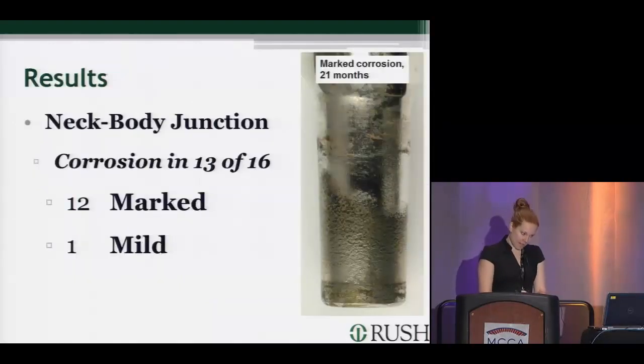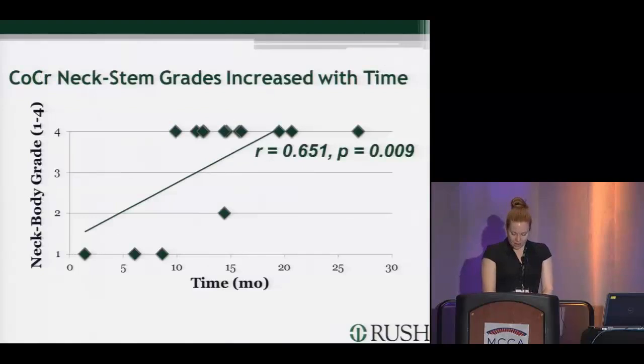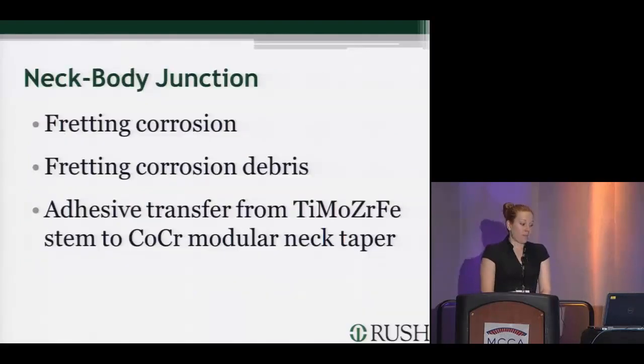So our results. At the neck-body junction, corrosion was seen in 13 of the 16 cases. 12 of these devices were graded as marked corrosion, and 1 of the devices was scored as mild corrosion. In a device retrieved as early as 8 months, marked corrosion was seen, and these corrosion grades increased with time. At the neck-body junction, the damage appeared in the form of fretting corrosion debris, and adhesive transfer from the beta titanium stem to the cobalt chrome modular neck taper.